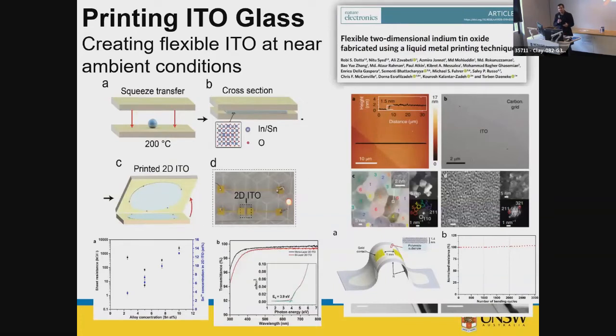Or ITO. We can make ITO. ITO is used in your mobile phone, conductive glasses. So it's made of indium and tin and oxygen. Indium and tin are both of them post-transition metals. So we thought, okay, why not looking at a method of going from melt to making this kind of layers? Everybody is either sputter or screen print them. I said, okay, this seems very simple. Why don't we do this?